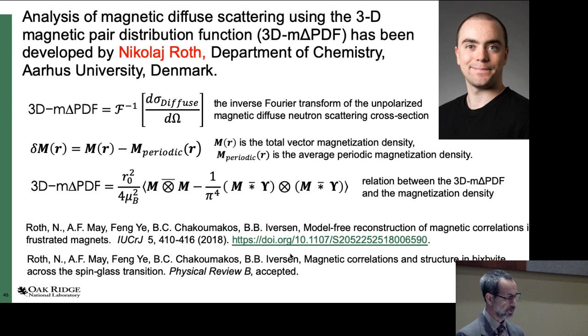Nikolai Roth, a PhD student at the Department of Chemistry at Aarhus University, who's collaborating with us on this project, has developed the relationship between the vector magnetization density and what we're calling the 3D magnetic delta PDF. It's simply the inverse Fourier transform of the magnetic diffuse scattering. We take into account the vector magnetization density, and the details of the mathematics are given in these two papers. The paper in PRB is about to be in print.